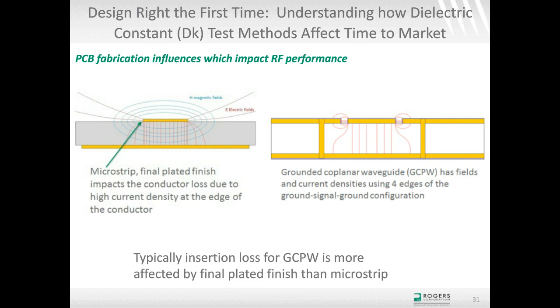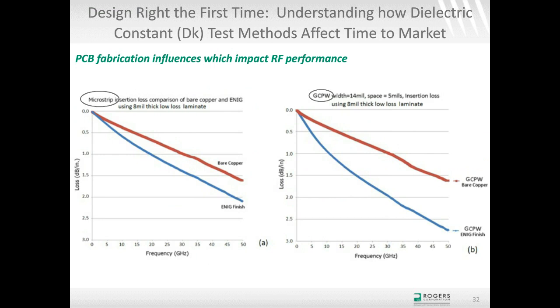And the reason there is on the coplanar layer where it's ground signal ground on the top copper layer, there are coupling fields between the signal conductor and the neighboring ground planes, and those coupling fields are basically using four edges of the plated finish. So there's current density on the sidewalls of those coupling fields, and that current density is actually using four edges of ENIG, and what happens is you get a lot more insertion loss when comparing apples to apples between a microstrip circuit and a ground coplanar waveguide, and that's what the charts are showing here.